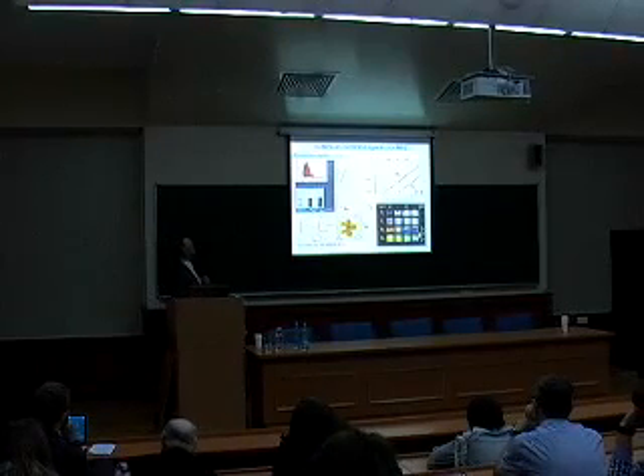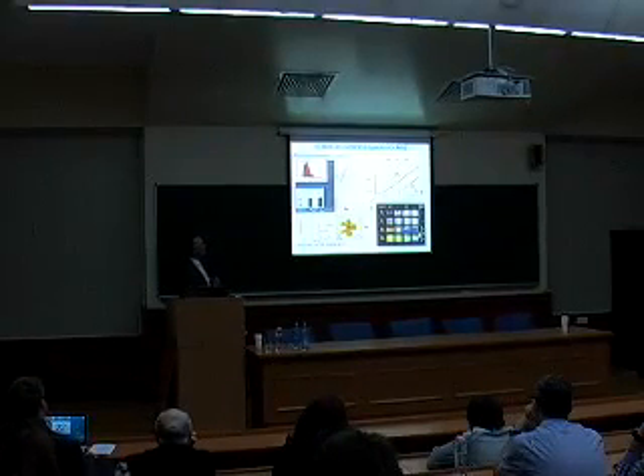Here you can see the first paper devoted to application of silicon nanoparticles for MRI, operating at proton frequency. We used very small nanoparticles created from porous material, but the size distribution was initially centered near 20 nanometers. You see an example of these suspensions. In diluted conditions, they are nearly yellow. And we observed shortening of both T1 and T2 relaxation times, and transverse relaxation shortening was the most efficient. We see the rate of such shortening, and we can calculate the relaxivity. And the main origin of such shortening is the interaction of electron spins, meaning silicon dangling bonds on the surface of porous nanoparticles, with proton spins.